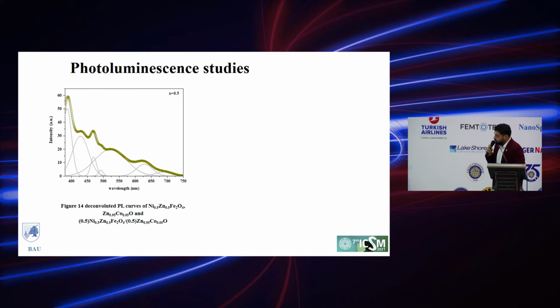We performed the deconvolution of the PL spectrum of the nanocomposite sample with x equal to 0.5, and the violet emissions were assigned to the zinc interstitials and the Zn2+ transitions in tetrahedral sites. The blue emissions were assigned to the Ni2+ transition in octahedral sites. The green emissions were assigned to the oxygen vacancies that cause distortion at the level of the oxygen metal bonds. And the red emissions were assigned to the Fe3+ transitions in octahedral sites.